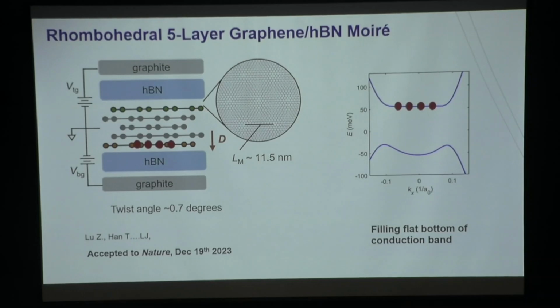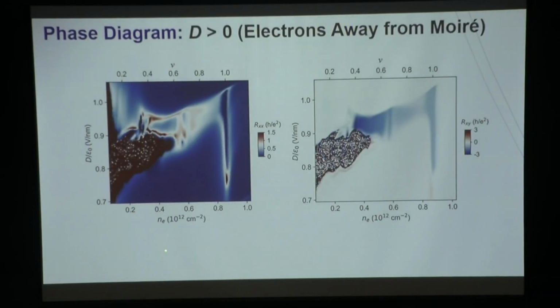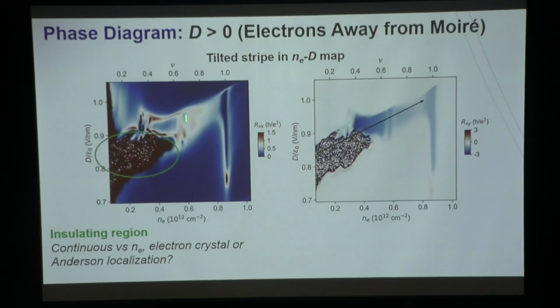But experimentally, in such a setting, what we found is that if you crank up the displacement field, you measure a region that is very bizarre in both longitudinal and transverse resistance. Overall, it's a tilted stripe in the charge density and displacement field map. While the lower density half of the stripe seems to be very, very insulating over a big charge density range. Okay, so we think this may be the so-called Wigner crystal formed due to electron repulsion, but we're not sure because we're not imaging it. While the higher density part of this stripe seems to have a lot of anomalous Hall signal.